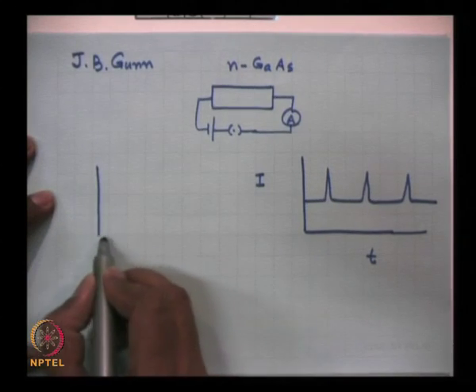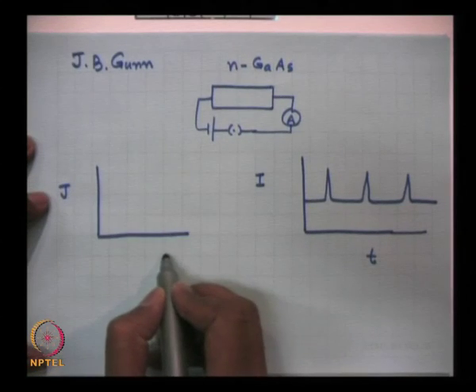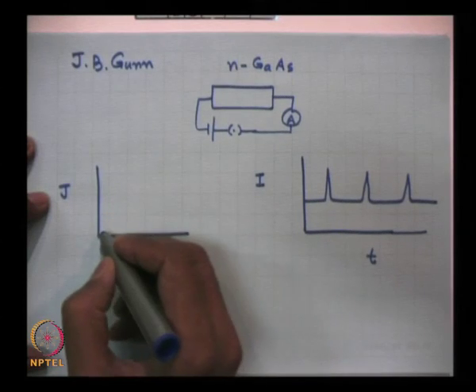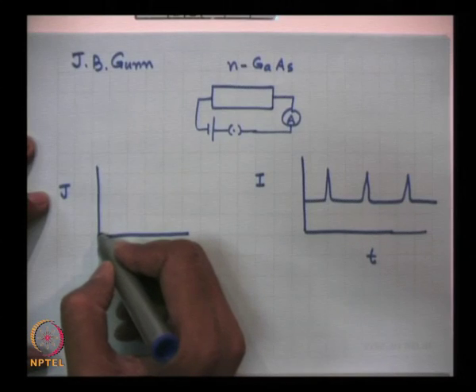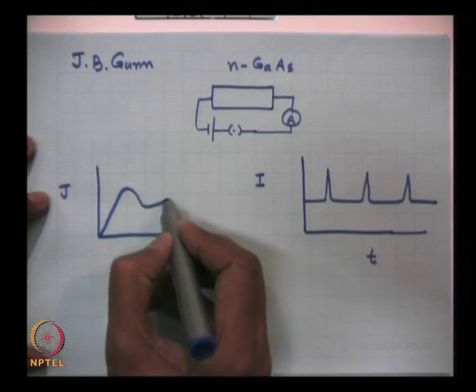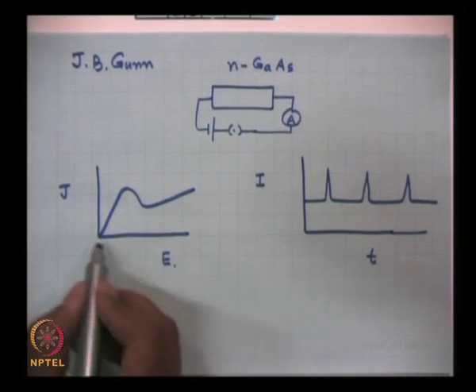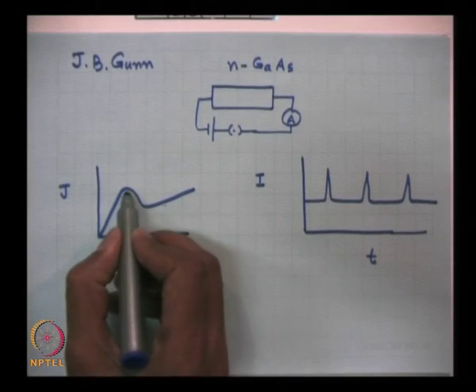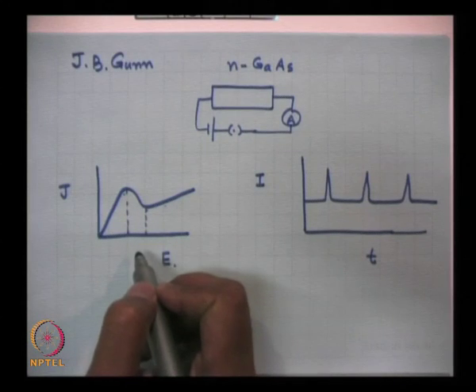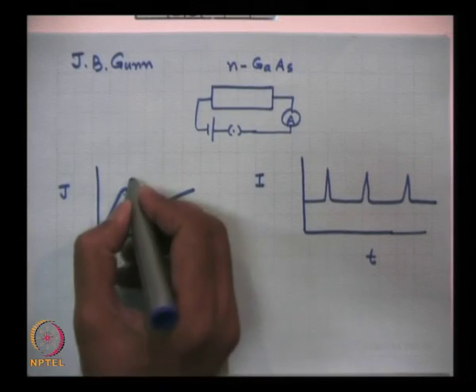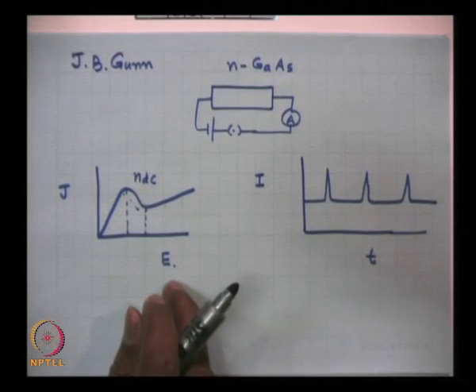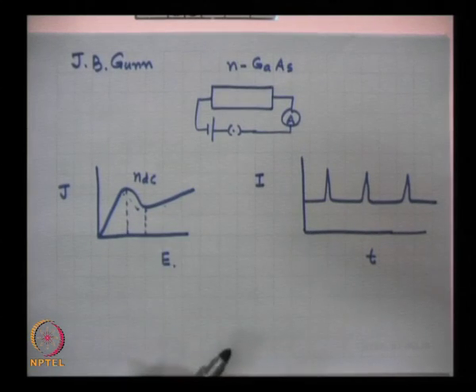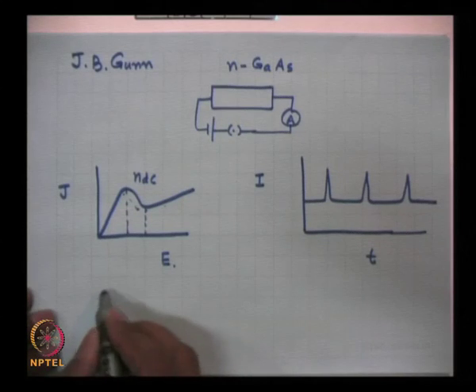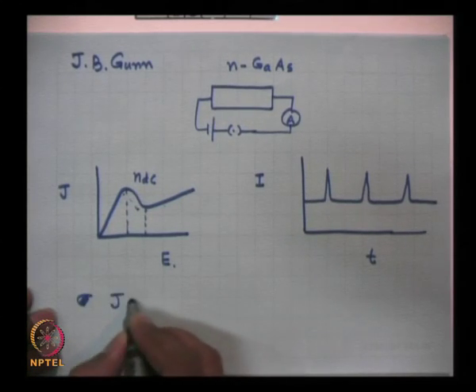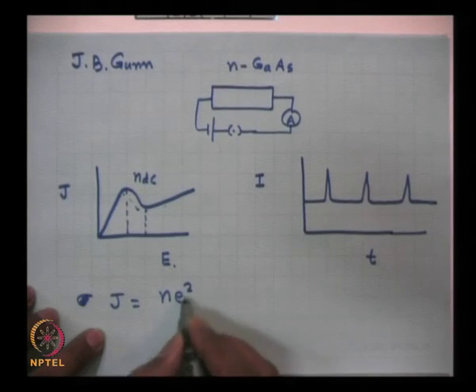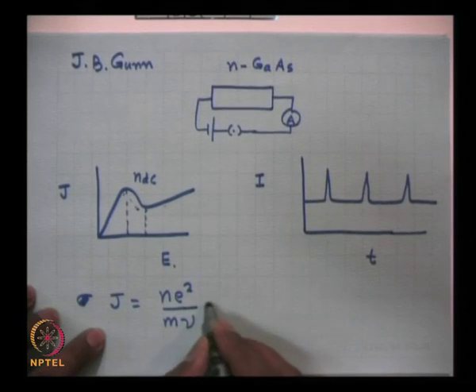People tried to understand, probably he himself tried to understand this. So, he says that if I plot a graph of current as a function of electric field, the graph was like this at low electric field when the voltage was low, then it goes like this, but then it behaves like this. The slope of this J versus E curve was different here than there. This region between this peak and this minimum is called the region of negative differential conductivity, NDC, because current decreases with the electric field, more the electric field less the current. That is something very spectacular. What happened? You just look at the expression for conductivity, or rather J equal to sigma E, and sigma is n e square upon m into nu into electric field E.